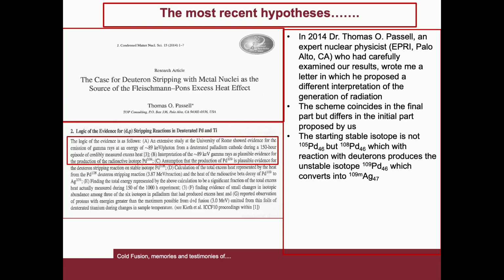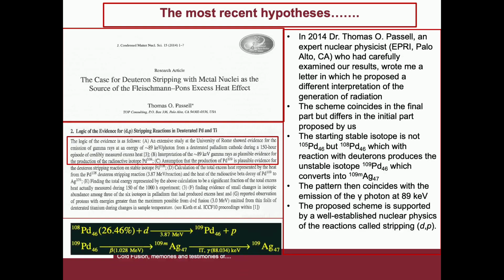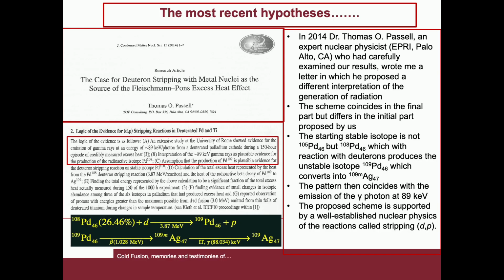The starting stable isotope of palladium is not palladium-105, but palladium-108, which by reaction with deuterons produces the unstable isotope palladium-109, which converts into metastable silver-109, as indicated here in the diagram. Palladium-108 is an isotope with 26% in natural abundance. The scheme then coincides with the transition to stable silver with emission of the gamma photon of 89 keV as the energy estimated by us.